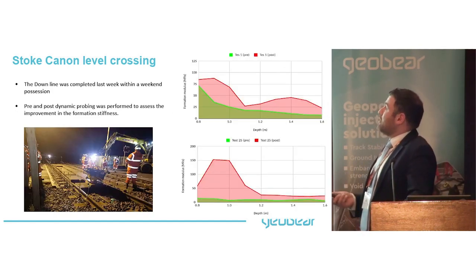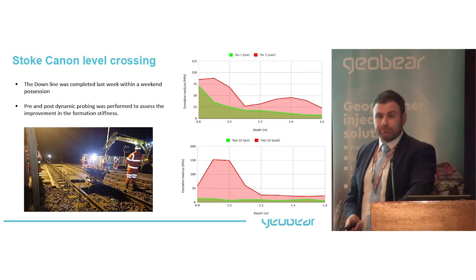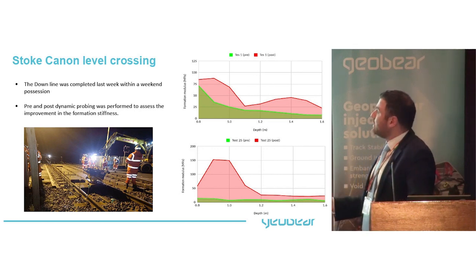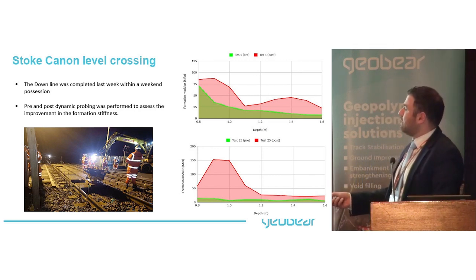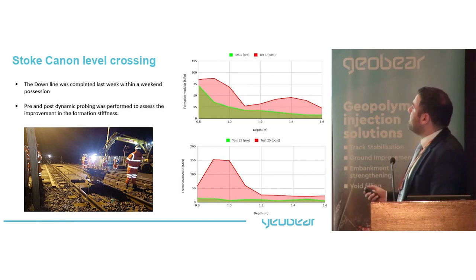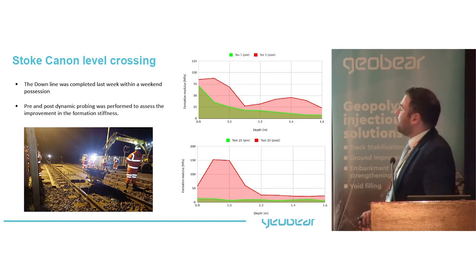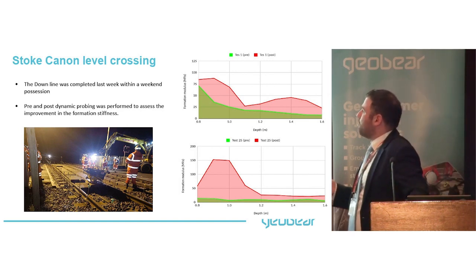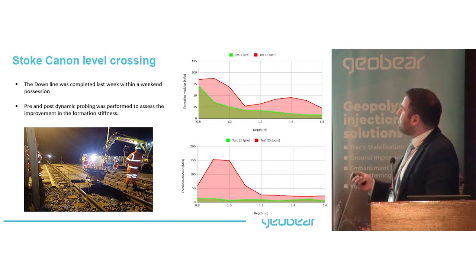We carried out pre- and post-dynamic probing to quantify the level of improvement in two locations, one on each end of the level crossing. We took the dynamic probing data and converted it into formation modulus. The green curve represents the formation modulus before treatment, and the red curve represents the readings after the injections.